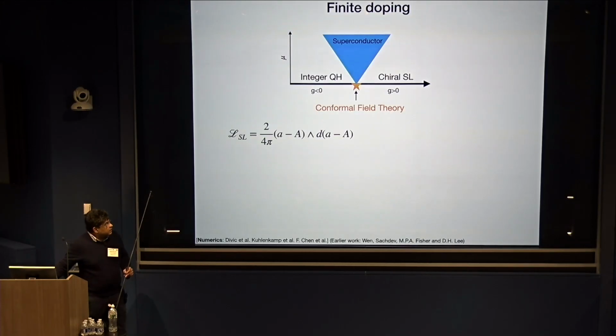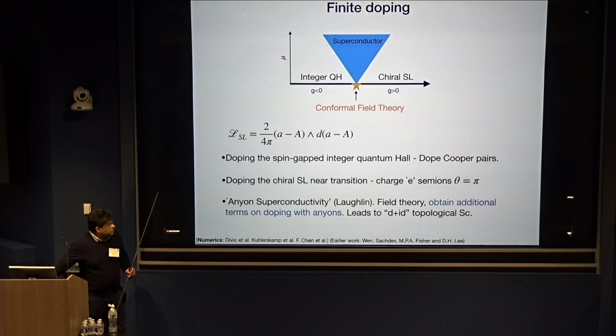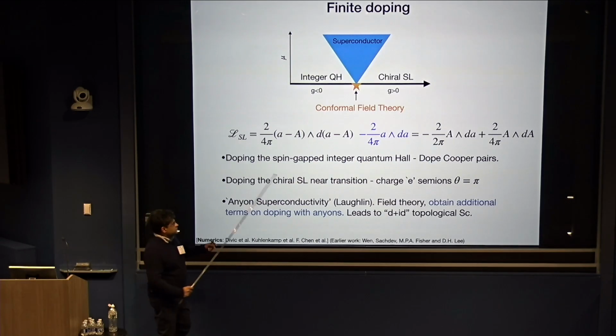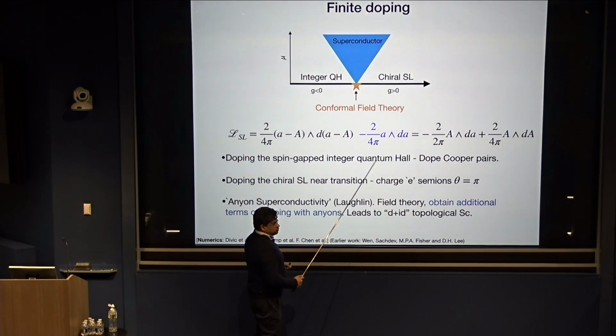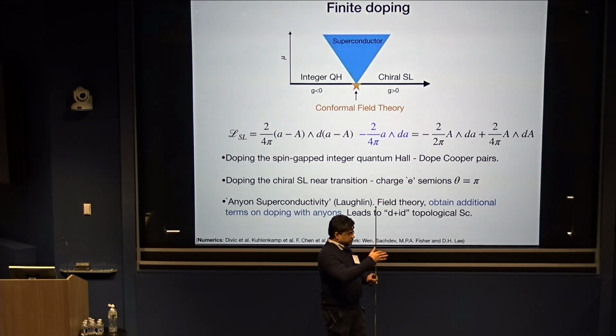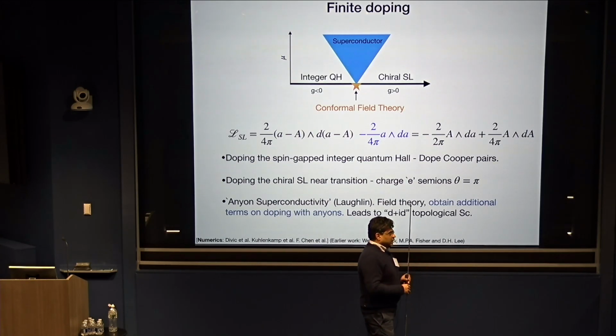Yeah, you're right. Everything is in this term over here. So what you do is you think of changing the density of particles, but you want to maintain the spin gap. If you think of a parton construction for this, say b times f, you're going to adjust the flux that f sees so that it accommodates a slightly smaller number of particles. So f is in a Chern band. You adjust the internal flux when you dope it to keep it in an insulator.